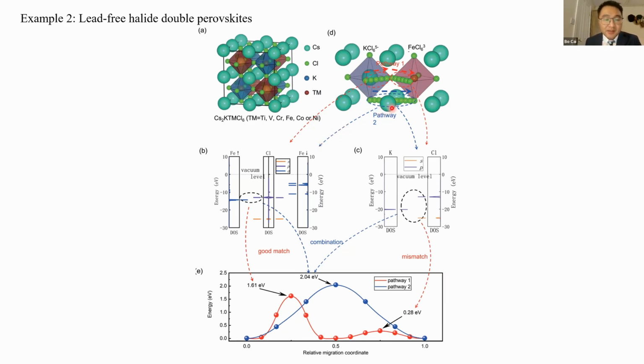The former part of pathway one corresponds to the breaking of Fe-Cl bonds. So we should check the DOS of iron and chlorine, although the center of this path is potassium. Similarly, we should check the DOS of potassium and chlorine for the latter part of pathway one. We found there is a good match between iron and chlorine. So the diffusion barrier of the former part of pathway one should be much higher than the latter part. Also, our CI-NEB calculations verified this result.